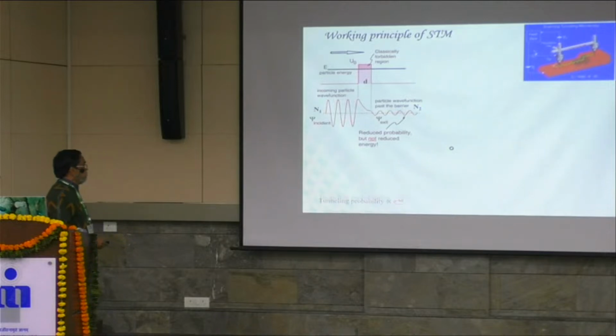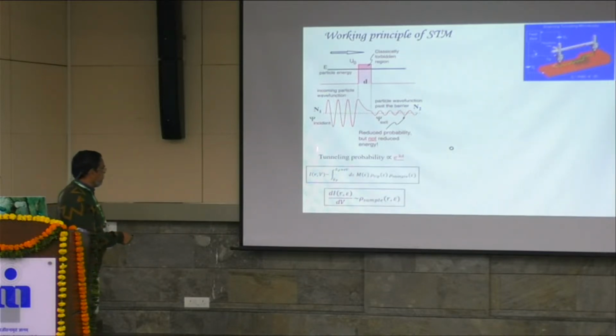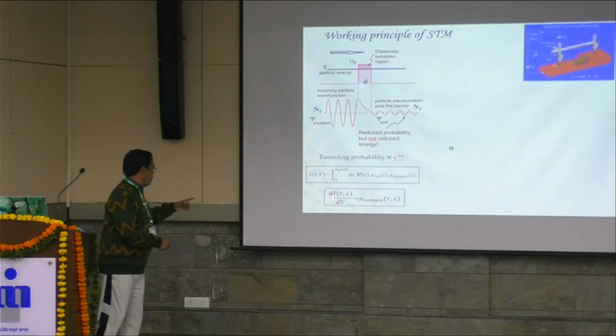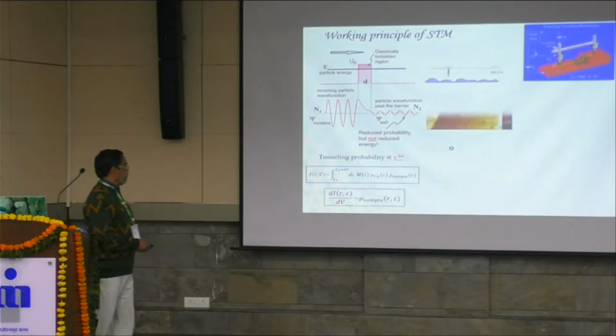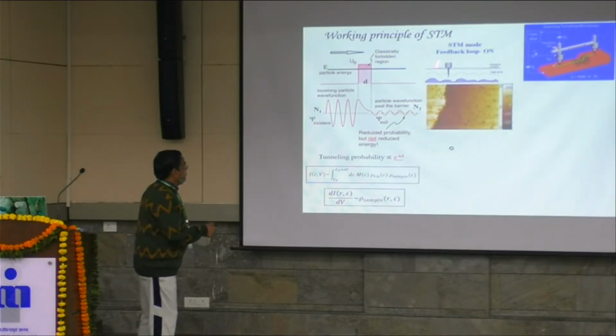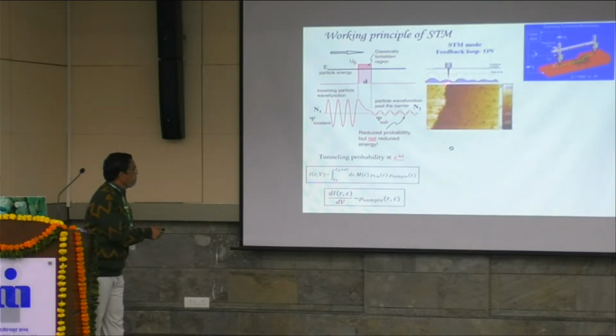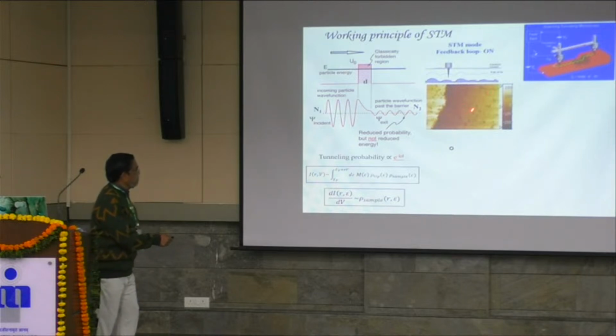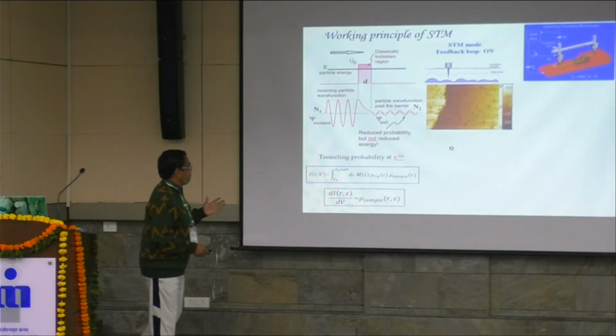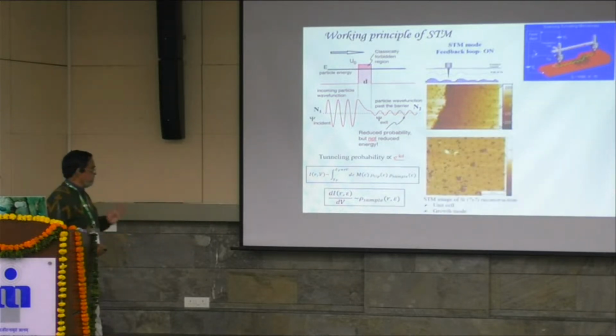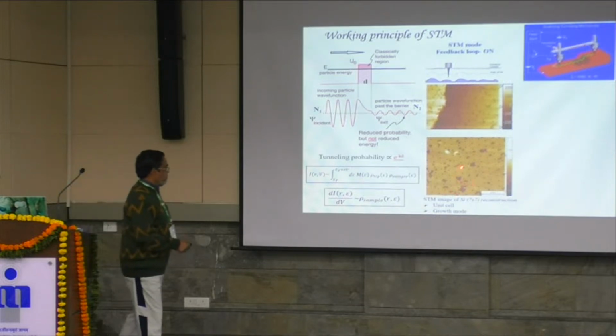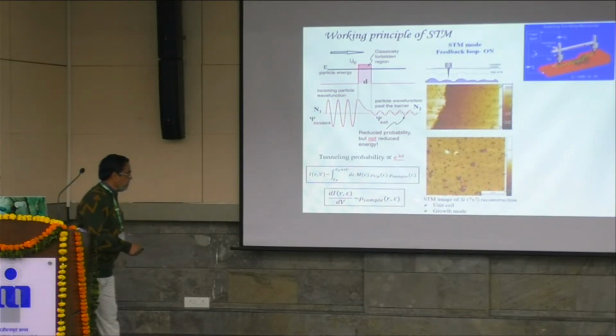So this I already talked about. These are the different equations which define the current, and if you take a derivative of that, you get a local density of states. So this is the cartoon. The tip comes very close to the sample, and this is silicon 111, and you can see this is the step. This is one set of atoms. This is another set of atoms. This is a silicon 111 7x7 reconstruction. It's a very easy thing to do in STM. This is all UHV STM, by the way.